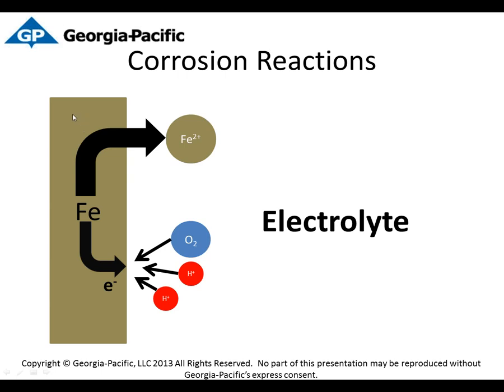And where this gets important is when we look at microbial influence corrosion, is that microbes are actually just changing this reaction. They change the kinetics of the reaction. They can change the speed of the reaction. They can change the corrosion product of the reaction. So that's really how the corrosion with microbes works, is they don't necessarily eat the material, eat the metal. They're just changing the existing corrosion reaction or corrosion mechanism.